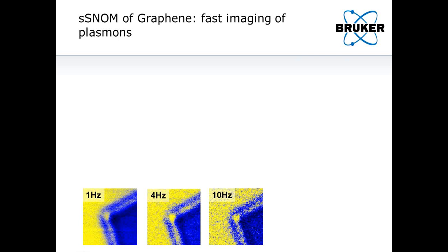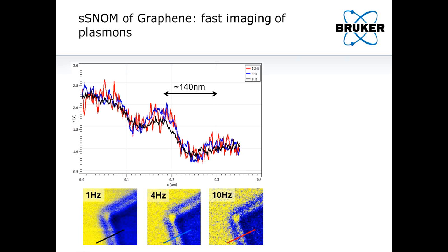On the next slide, I show three sets of images obtained at different scan rates. These images demonstrate that you do not have a loss of spatial resolution. They also allow us to extract the length scale for the graphene plasmon. We do not lose this ability if we scan fast. We can still determine the length scale.